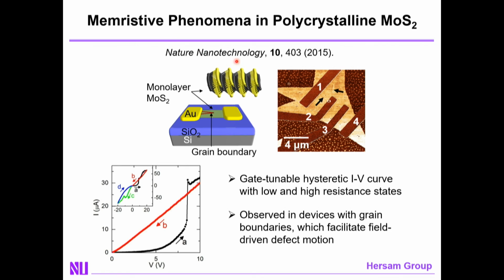The way we do this is an interesting case. It's polycrystalline MoS2. Polycrystalline MoS2 is mixed-dimensional in the sense that it's a 2D material, but the grain boundaries that are present in the polycrystalline material are one-dimensional in nature. And what we observe when we look at current voltage curves in polycrystalline MoS2 is that initially the device will start in a high resistance or low current state, but at some critical voltage it will switch into a low resistance or high current state, and it will stay in that state until you go to the opposite bias polarity. This two-terminal strong hysteretic loop is the characteristic behavior of a memristor.